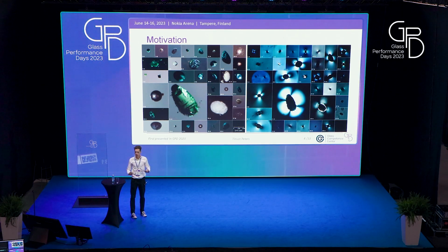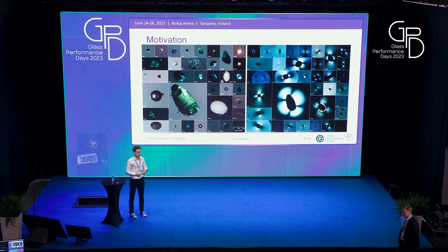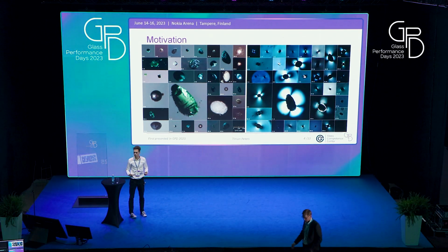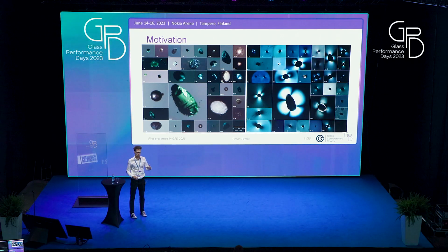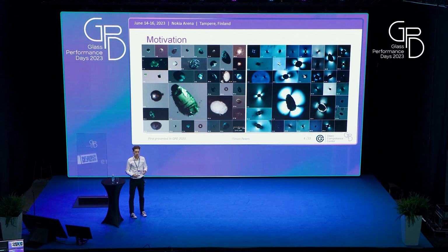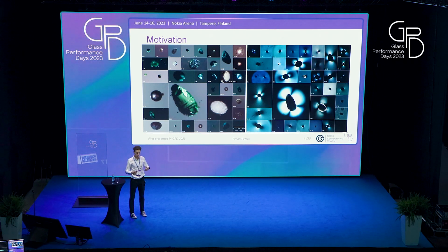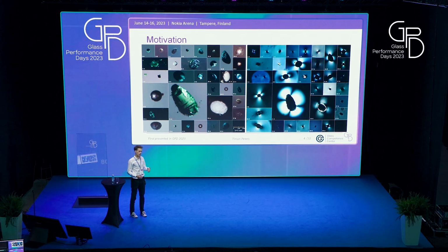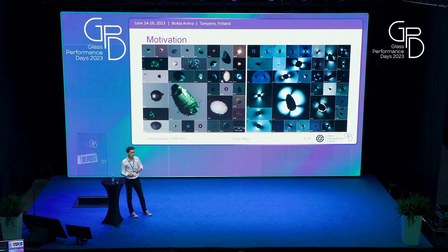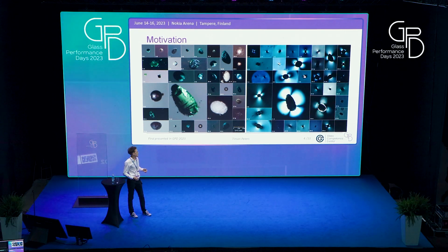Generally, if you get glass from a manufacturer, you will find a lot of small defects. That's because if you produce glass, you will always have those defects, and you will only sort out those that can become visible to the customer. So that's usually around 400 or 500 micrometers, after which you sort inclusions out, and everything below stays in the glass. But there are some inclusions that can become critical even below this size.